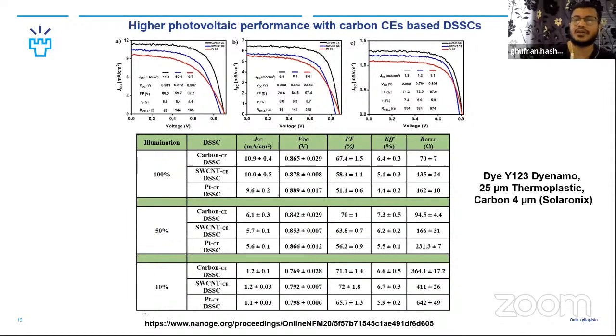It is the paste from Solaronix, and when you print you get a thickness of around 4 to 6 micrometers. Because the previous paste of carbon nanotube was just 1 micron thick, you have to adjust the thickness of the thermoplastic. So that's why we decided to use the 25 micrometer thermoplastic. And as you can see here, this is a screen printed high temperature paste which you print and then sinter at 400 degrees.